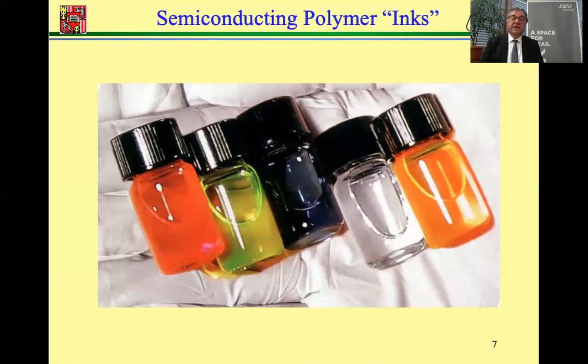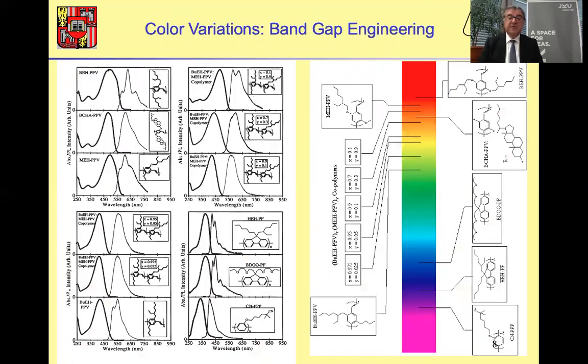And these inks I have been mentioning can be prepared for different colors, for different materials. This is actually the biggest advantage, for my taste. I'm educated as a physicist, as a semiconductor physicist. And even though I'm now professor for physical chemistry and moving more and more to biological materials, bio-integrations, etc., still the semiconductor physicist in me is fascinated by these organic semiconductors because you can change the band gap. You can change the properties of these semiconductors by chemical synthesis, by slight modifications of the side chains. The whole polymer chain can have a very different band gap. This is something which is very difficult to achieve in inorganic semiconductors.